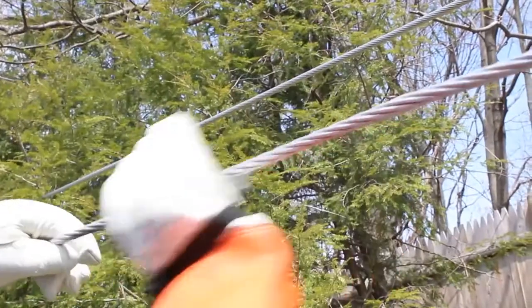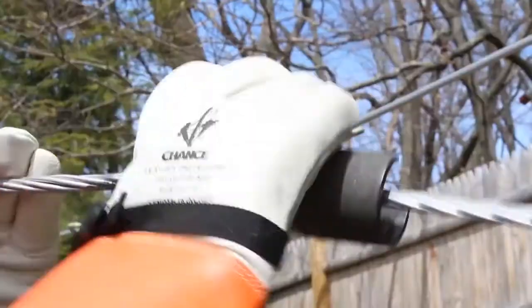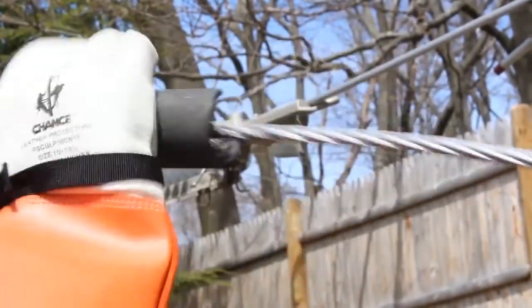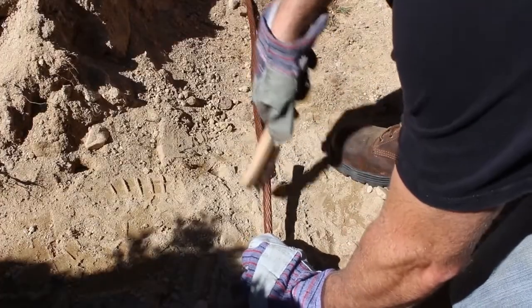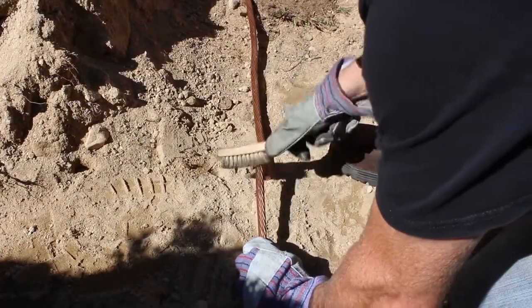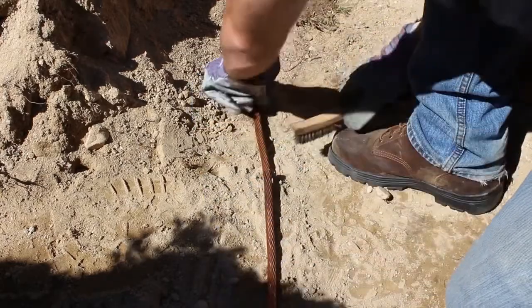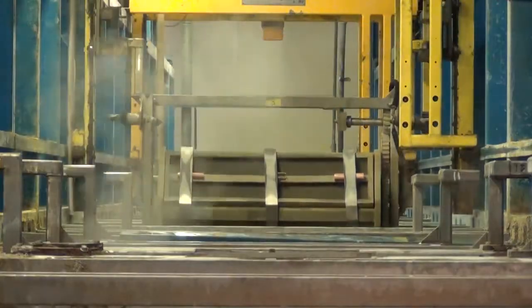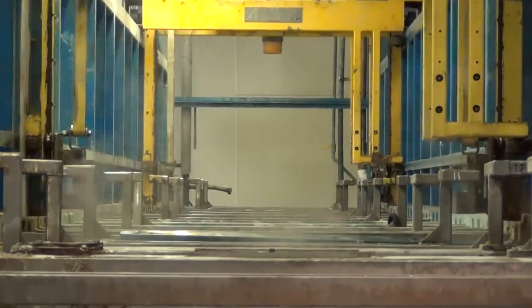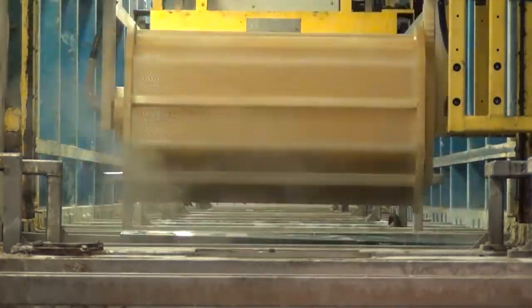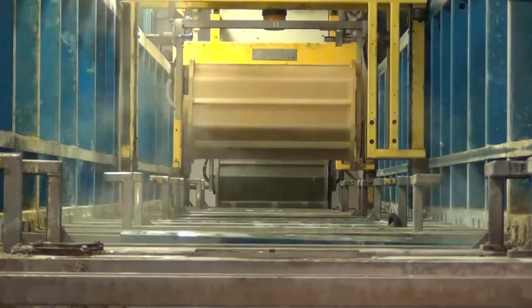The best way to do that is with a wire brush. One of the major causes of failure in electrical connectors, particularly in the utility overhead application, is that the aluminum oxide was not removed prior to installation. Wire brushing is the simplest and least costly way to remove that oxide. And in general, you only need to wire brush the conductor. Burndy aluminum connectors are specially treated at the factory to remove the aluminum oxide from the surface, and then they're sealed. So by the time they get to the site, there are no aluminum oxides on the surface.